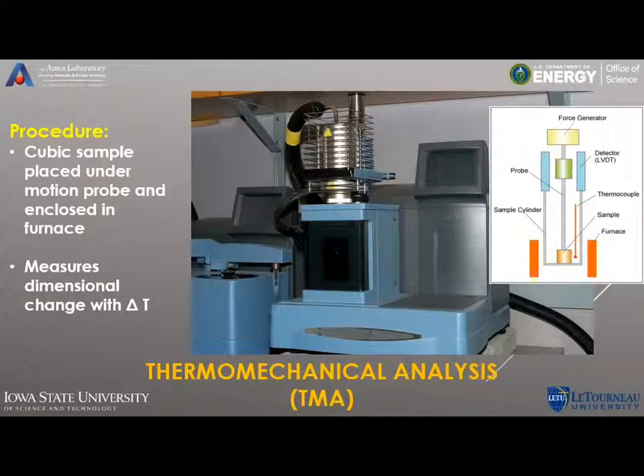One last method for analyzing these composites was thermomechanical analysis, and that's abbreviated TMA. In that, you take a cubic section of polymer material, and you place it under this glass probe, which presses down with a certain force. And then the furnace is brought down over the sample, and a thermocouple measures change in temperature as the probe presses against the sample, and the temperature is ramped up over a range. And so effectively what you're doing is measuring the dimension change of the sample, or the change in volume of the sample, with a rise in temperature.